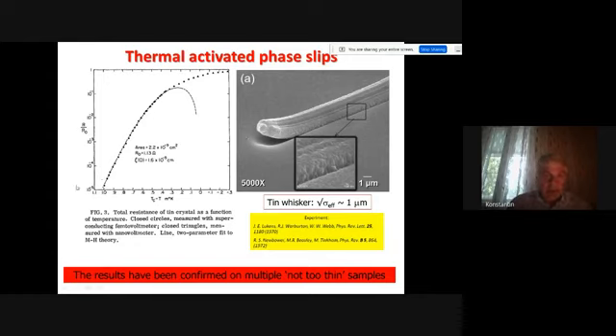The vertical scale is the logarithmic scale of the resistance, and the horizontal scale is temperature counted from the critical temperature. So 0 corresponds to the critical temperature. And within the transition width of about 1 millikelvin, the resistance drops 5 orders of magnitude, but still the width of the transition is not 0. It is perfectly described by the model of thermal fluctuations, which has been nicely confirmed by these experiments.